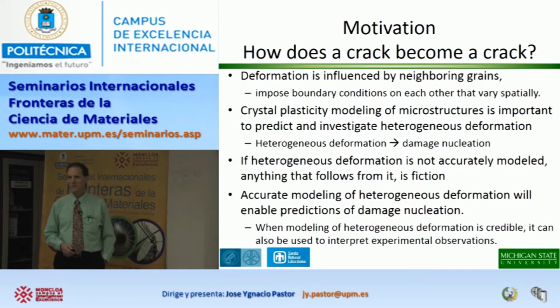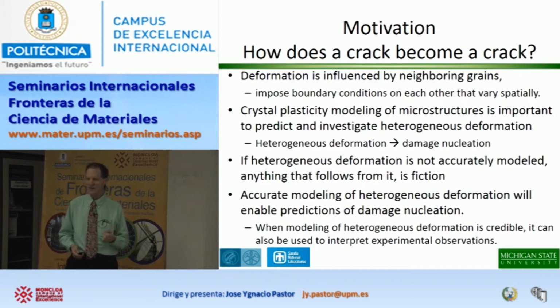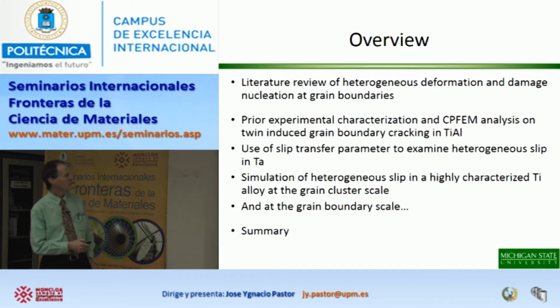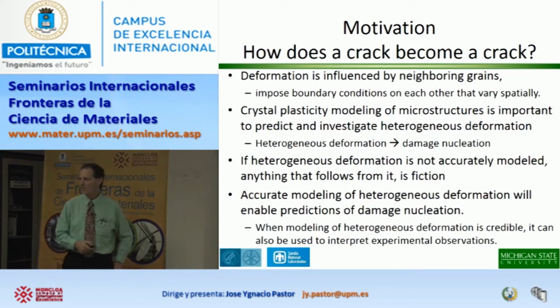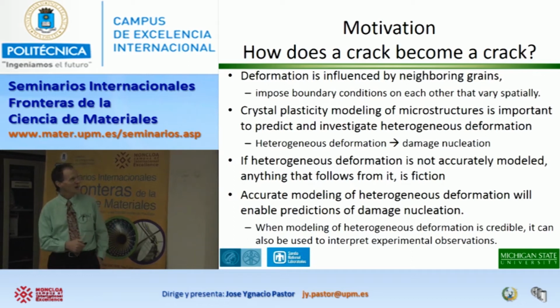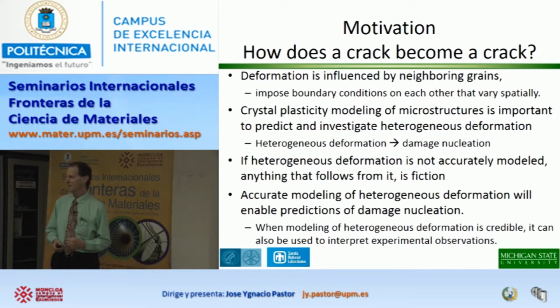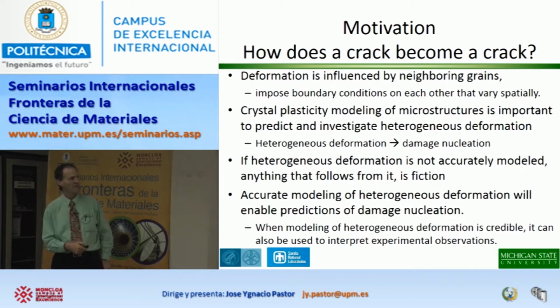So the motivation for my work is basically, how does a crack become a crack? And that's a deep question, because you think of a material that's in good shape, and then sometime later it has a crack in it, and how did that happen? So the question is, what happens immediately before a crack nucleates? Well, clearly, deformation is highly influenced by the neighboring grains in a polycrystal. Essentially, the neighboring grains impose boundary conditions on any given grain. And the boundary conditions are different, because every grain has different neighboring grains, and the way that each grain deforms is different. And so in order to really think about what leads to the conditions where a crack might occur, crystal plasticity modeling of microstructures is important.